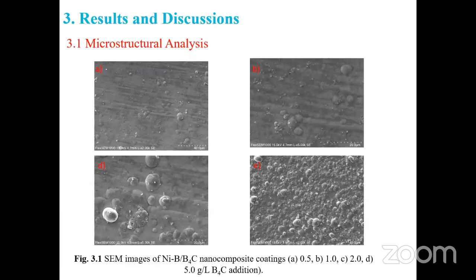Results and discussion. Figure 3.1 shows the SEM images of nickel boron, boron carbide nanocomposite coatings: A 0.5, B 1, C 2, and D 5 gram per liter boron carbide addition. According to the figures, as the amount of boron carbide added to the bath composition increased, the surface roughness increased. The main reason for that is the increase in the amount of second phase included in the coating structure, causing an increase in volume on the coating surface.